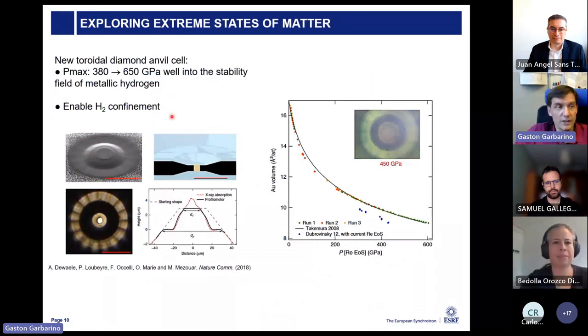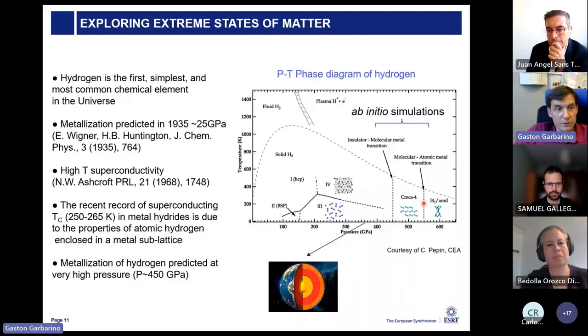In order to reach very, very high pressure, which is a very high technological activity, in the last years we were able to increase the pressure limit to the order of 6 megabars, the order of 6 million atmospheres, by modifying the shape of the diamond. We are drilling a particular shape on the diamond to generate a very small cavity, and this shape allows us to study materials up to 6 million atmospheres. This allows us to really expand the pressure-temperature domain of the samples.